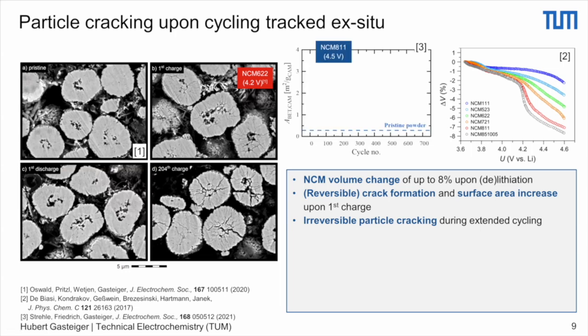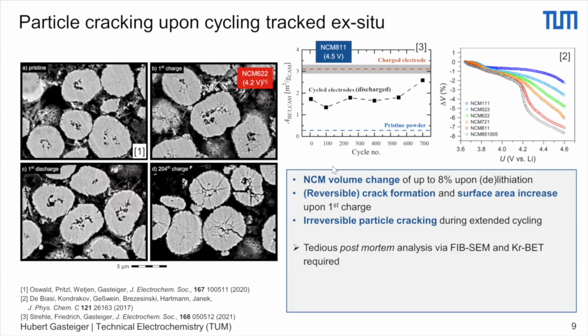If we now measure the BET surface area of materials, we can measure the BET surface area of the pristine powder. As I said before, it's about 0.3 square meters per gram for these materials. We can also measure the BET surface area of a charged electrode. That, of course, can only be done with krypton BET because you cannot have so much active mass in your instrument. And then we can follow the BET surface area of cycled electrodes over the course of cycling.